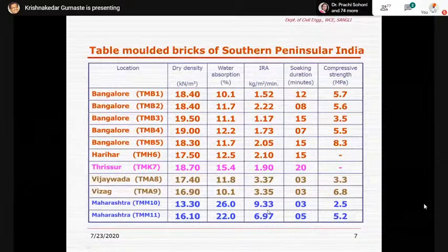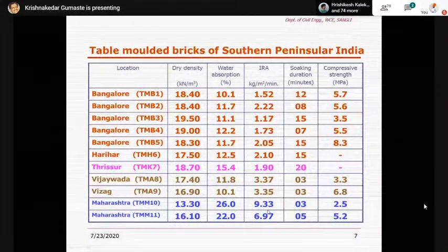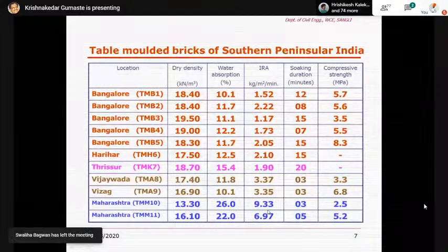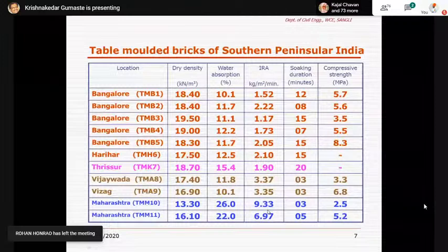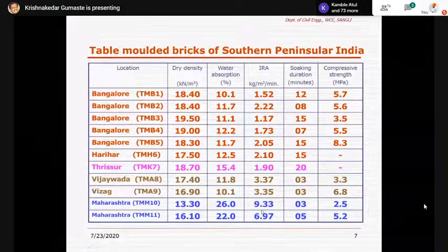And this becomes very, very important as far as whether you use dry bricks or completely saturated bricks, thereby affecting the performance of the mortar. The brick can absorb all the water from the mortar, and thereby improper hydration of the mortar can lead to improper masonry performance, which is why IRA becomes important. And thereby, the condition of the brick to be used during construction is that the brick should neither be completely saturated nor completely dry, and thereby the bricks need to be partially saturated.